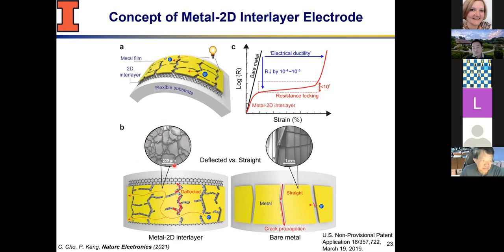And then, because we're interested in using these as electrical conductors, we decided to simply measure the conductance or resistance of the metal versus strain. So it's not a strength, it's a resistance versus strain. And if you plot the resistance in log scale, the bare metal looks like this. It's almost very straight going up. And so this almost reminded me of a ceramic type of material, very brittle material, right? If it was strength.